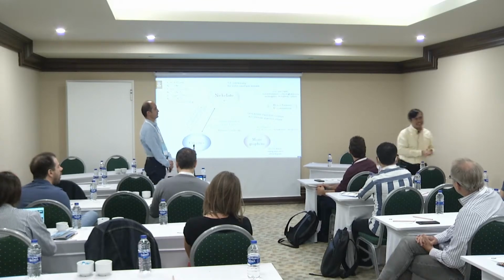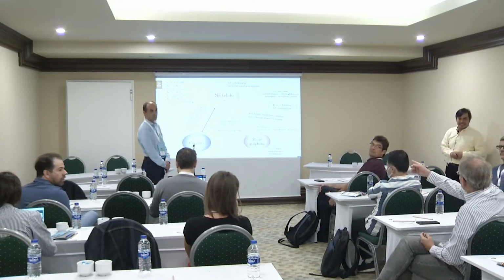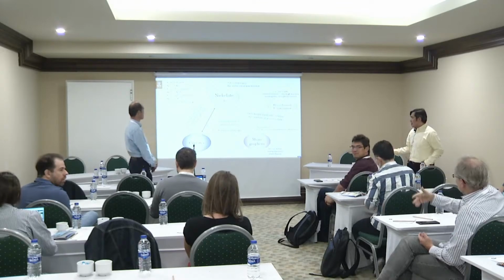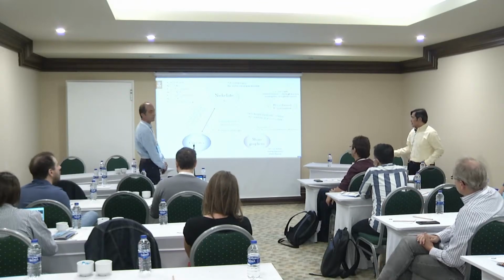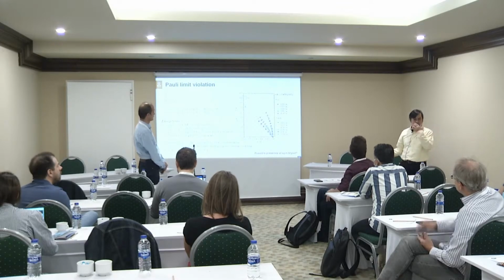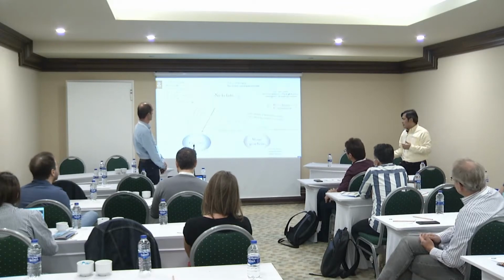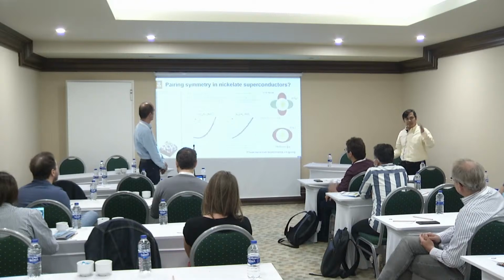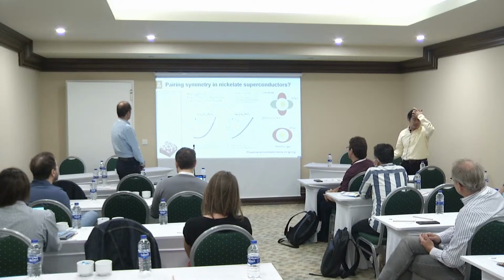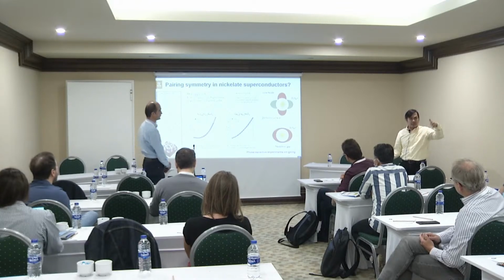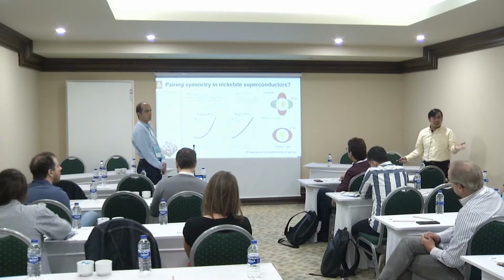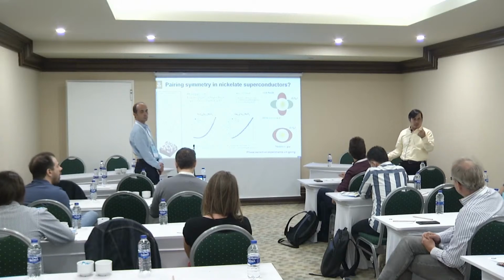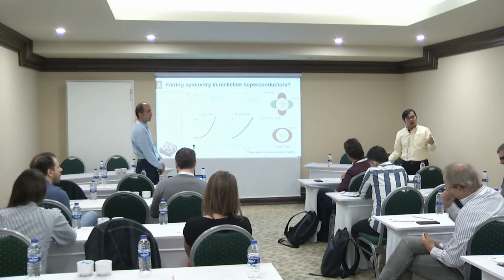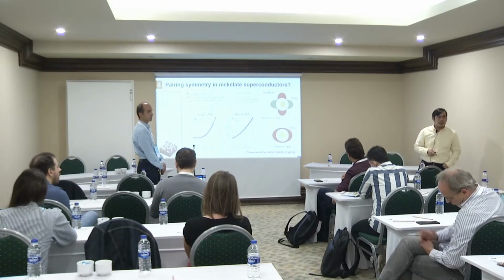To my understanding, there are still oxygen contributions, I believe. We observe this in the thickness dependence, where there is a change in the pre-peak before the main peak of the nickel, which is likely because of the hybridization between the 3d and oxygen. So I think it is dominantly 3d x² minus y² with a small hybridization with oxygen. Okay, thank you.